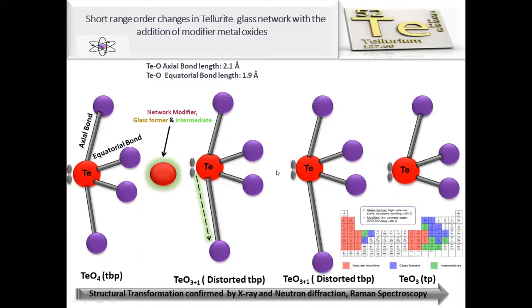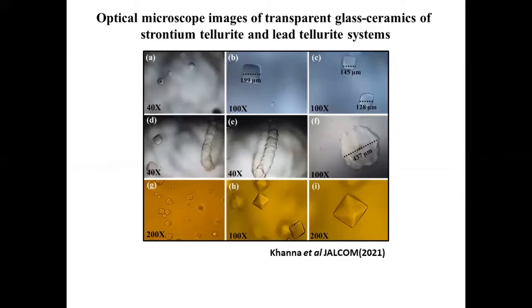We generally prepare tellurite glasses. In fact, we always prepare tellurite glasses by adding some network modifiers, because tellurium dioxide has very poor glass forming ability. By itself, it forms glasses with difficulty. And some very interesting effects are seen when you add some metal oxides like strontium oxide or lead oxide to the tellurium dioxide. You get glassy phase. These are the photographs of some of the lead tellurite and strontium tellurite samples prepared by quenching method.